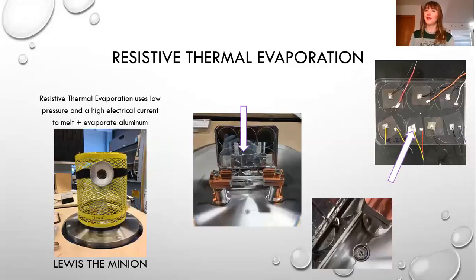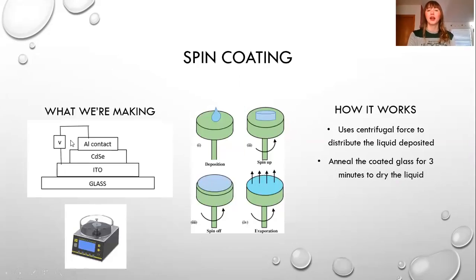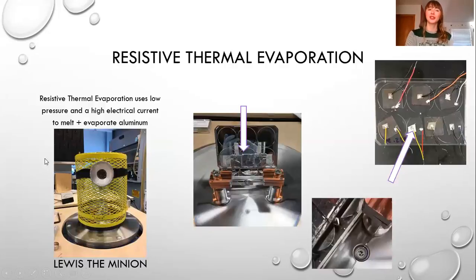Resistive thermal evaporation is how we put that aluminum contact, like you can see here, onto our cells. So this is my favorite lab partner, Louis the Minion. But basically it's a giant glass dome that's connected underneath. The middle picture here is inside of the dome. We have this basket that we put aluminum chunks into. We set up our solar cells with a mask over them, so we only get aluminum deposited on a small section of our cadmium selenide layer.